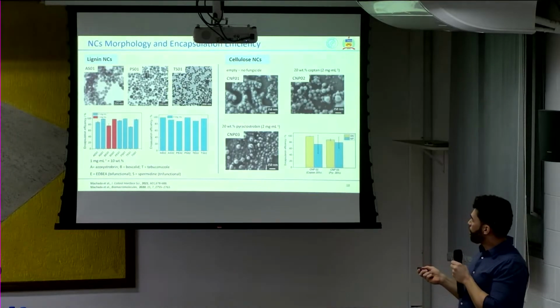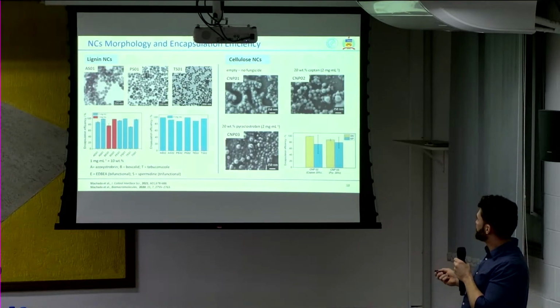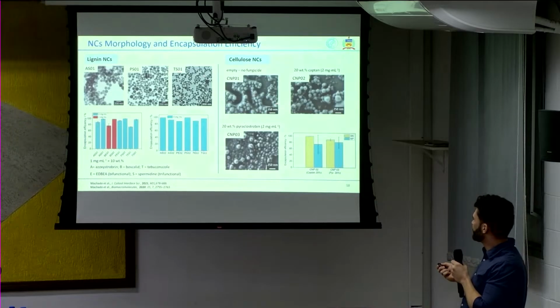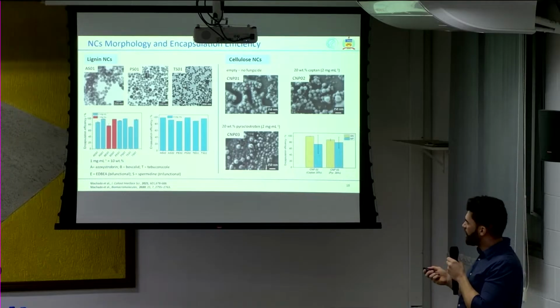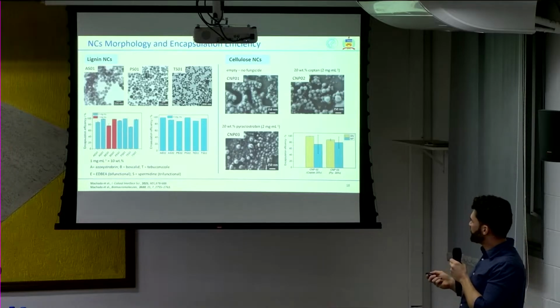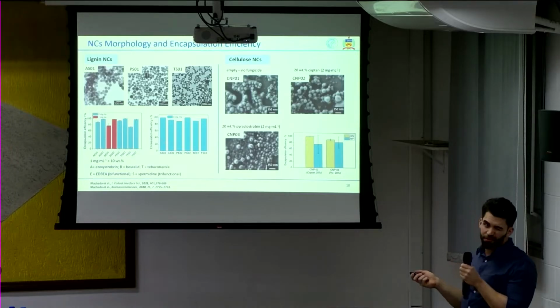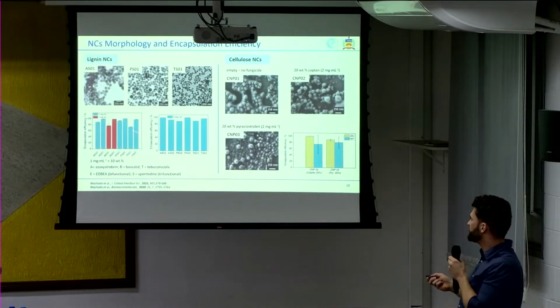So these are the particles, lignin nanoparticles and cellulose nanocarriers here because they're loaded. These are TEM images. These are SEM images. I would say the diameter is around 200 nanometers. And the encapsulation efficiencies were above 70% for all formulations tested. So high encapsulation efficiency, I would say.